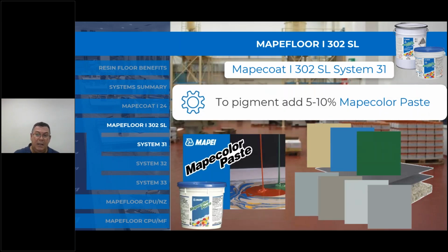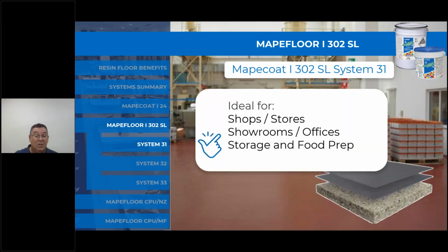So into the unpigmented epoxy goes a pigment paste, so the Mapei colour paste. The 15 kilo I-24 and the 20 kilo Mapefloor I-302 SL require 2 pigment packs to be added in mixing, and it comes in this range of standard colours. This system is ideal for shops and stores, showrooms, offices, storage and food preparation areas, and generally a lighter duty type application because it's not considerably thick in its coating thickness.